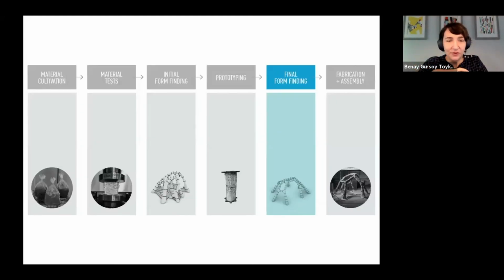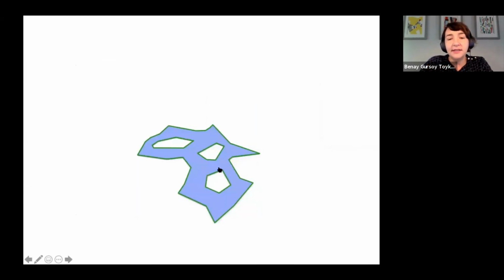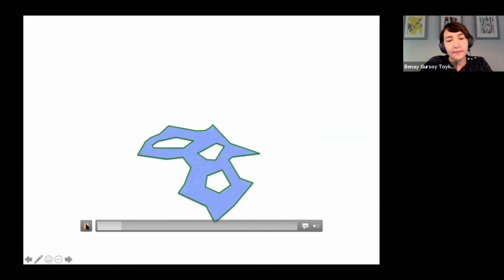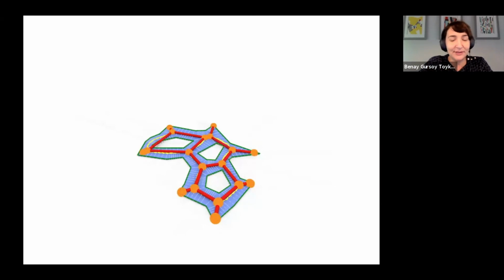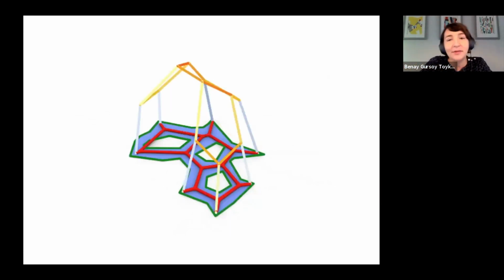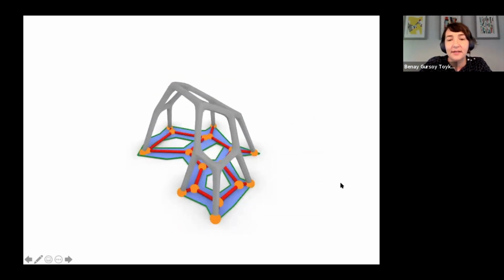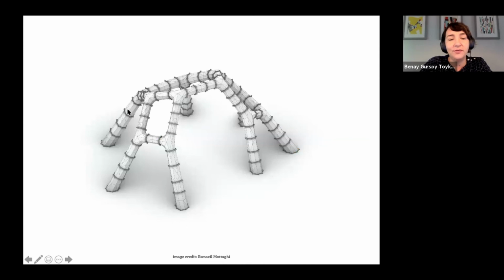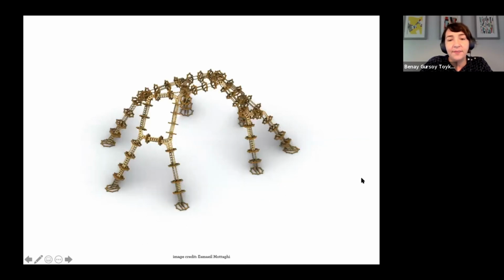After making the prototypes, we learned about the size constraints for better mycelium growth, but also how to best fill the formworks and how to best compress the substrates within them. Based on these, we made some changes in the formwork design, and these informed the final form finding, which was simpler than the initial form that we submitted for the competition entry. It was made out of 64 components, and each of those formworks had an interior skeleton. This is how it looks.